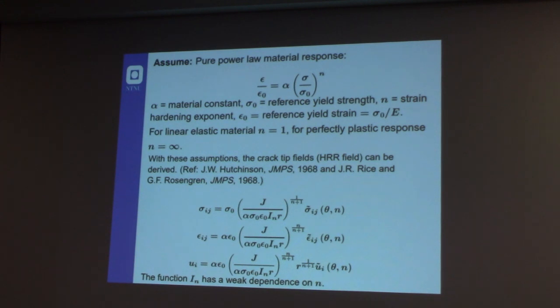You can also use a Ramberg-Osgood equation for your material, but what you are obtaining is a stress field that is a function of the J integral, and of an angular function of theta that still depends on n. This is also the reason why the stress field is not scalable in terms of loading, so the superposition principle is not valid, because the angular functions also depend on the strain hardening material property. And after that you have this contribution in the exponent of n, which is a material property parameter.